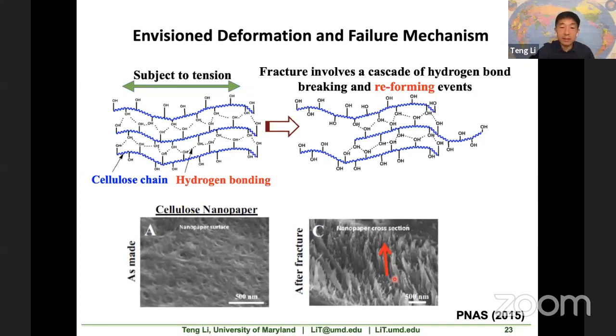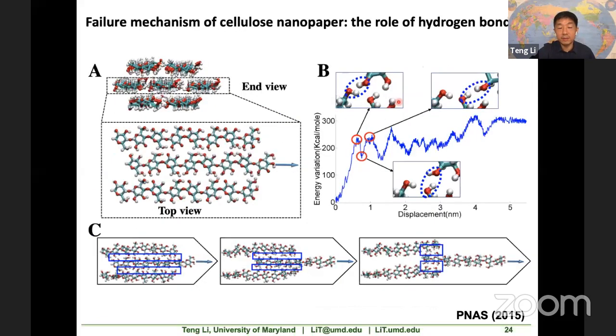To verify the atomistic deformation and failure mechanism, we use molecular dynamics simulations. So we simulate seven cellulose chains here. This is the end view. So we let the middle one slide off from the surrounding. If you view from the top, I'm not plotting the top two and the bottom two, just plotting the middle three for visual clarity here.